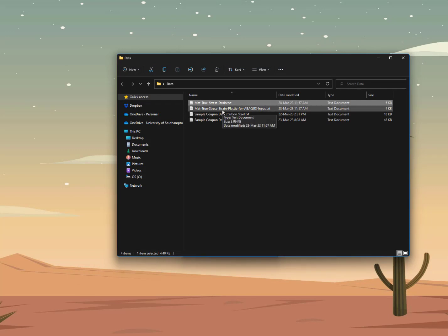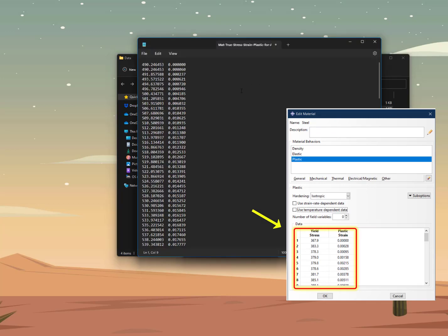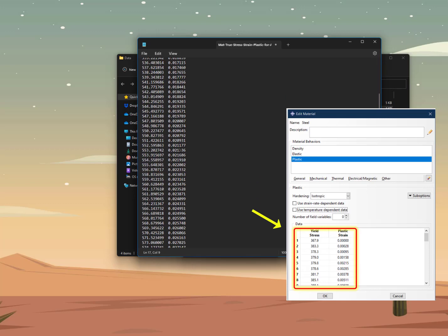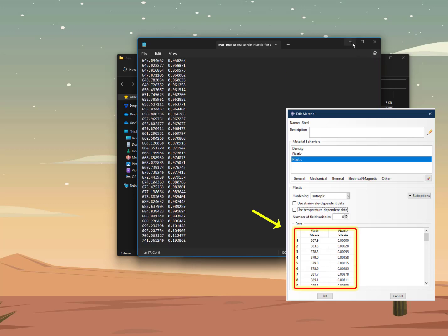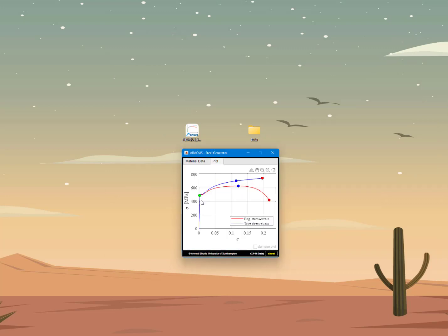Abaqus expects the true stress-strain data but only the plastic strains, organized with stress in the first column and plastic strain in the second column. So if I open that file I will find this data organized accordingly — the first column is the true stress and the second column is the plastic true strain. This data I can copy directly and paste into Abaqus when defining the plastic portion of the material. If I go back to the Plot tab, I can now see a new curve — the true stress-strain curve in blue — with the key points indicated on it as well.